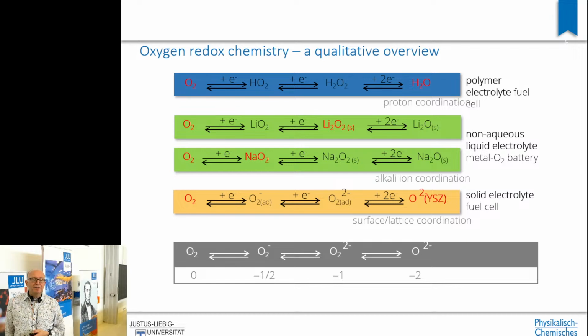And the oxygen comes then from the gas phase, enters into the electrode, gets electrons, forms a product, and this product, in fact, depends very much on the counter cation. What you see here is the redox scheme of oxygen from the molecule dioxygen to O2 minus, depending on the counter ion, and in the middle is sodium and lithium.